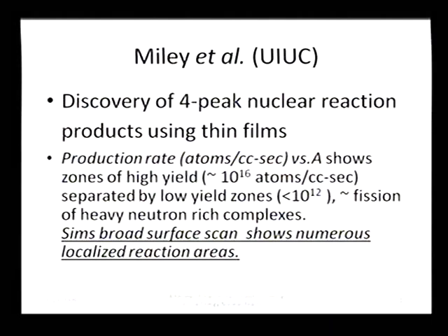The production rate, which he postulated in terms of atoms per cubic centimeter per second versus A, shows zones of high yields in the peak areas of about 10 to the 16th atoms per cubic centimeter per second, with low yield zones. He basically looked at the isotope abundance using SIMS, broad scans of the surface, and was able to show that there were localized areas of reactions.